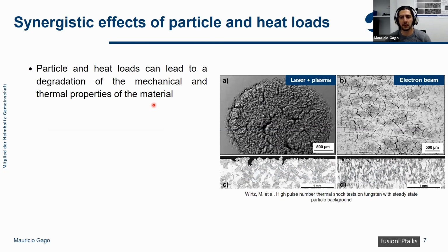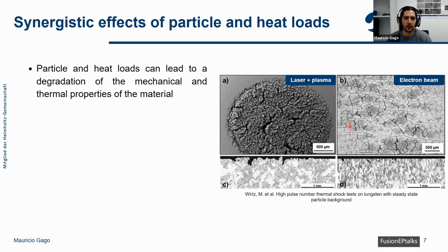So what effects will these kinds of loads have on PFMs? Depending on how the materials are tested, the results can be very different. As we see here, we have one tungsten sample tested with laser and plasma, which is very similar to what I will show you afterwards in my results. In here, we have the synergistic effects of both. On the right, we have a sample tested in similar conditions under an electron beam, but in this case, only heat loads were applied. Of course, between laser and electron beam, there are certain differences, but we can also see very clear differences if it's with plasma or without plasma. And these kinds of effects we would like to understand more clearly.